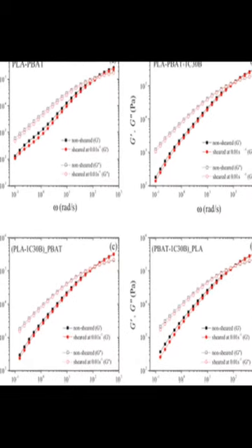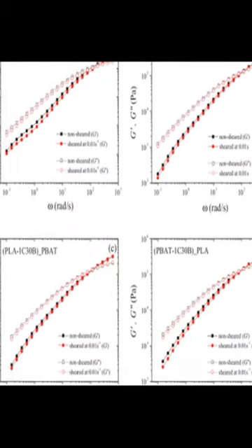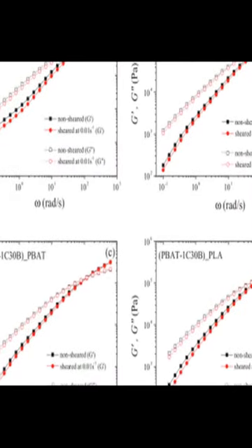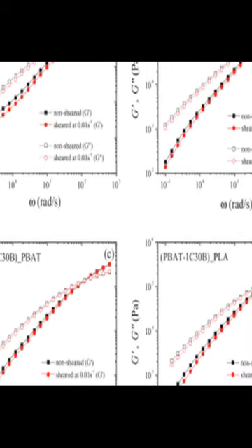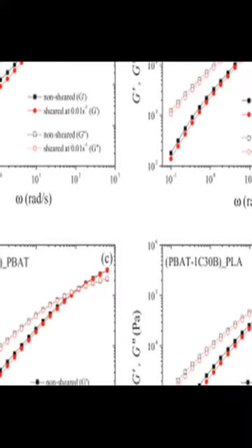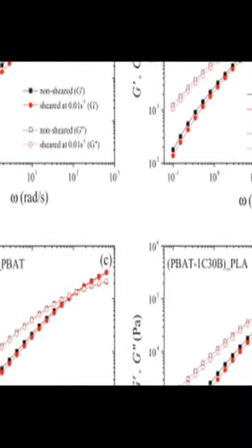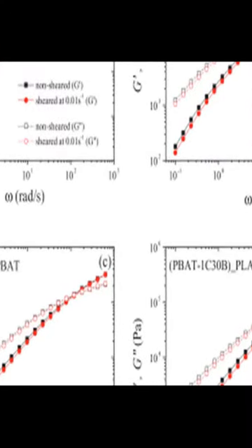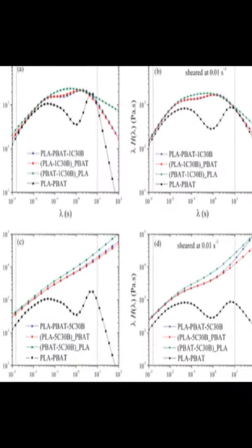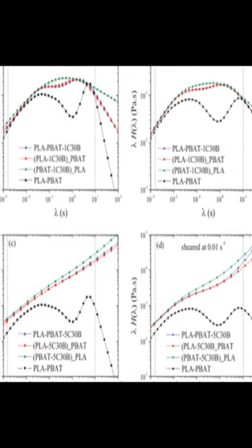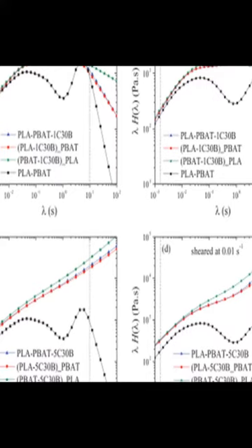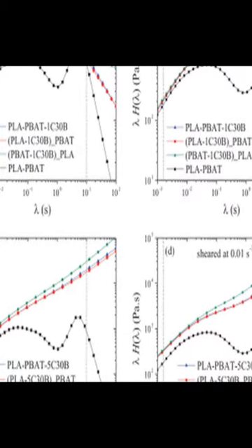The study examined the effects of organically modified clay nanoparticles on the molecular relaxation behavior of a molten blend of polylactic acid (PLA) and poly-butylene adipate coterephthalate (PBAT). The nanoparticles were added in varying concentrations and three mixing strategies were employed to control their localization within the blend. Small-amplitude oscillatory shear (SAOS) and stress growth tests were conducted to determine how the nanoclays interacted with the polymer components and their influence on the molecular relaxation behavior.